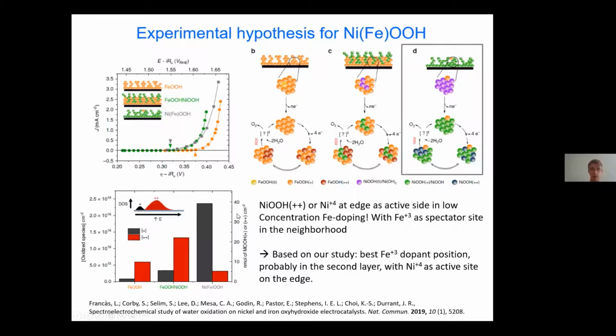But first, we mentioned something, an experimental study, a photoelectrochemical study, where they used UV-Vis to detect what is now the active state during the catalysis. So the system that we have studied computationally is actually the system in gray. That's a nickel OOH with a very low amount of iron, lower than 5%. So in this system, we have actually as active site nickel 4+, and then iron 3+ is present in the neighborhood. And let's see whether this is also what we can find computationally.